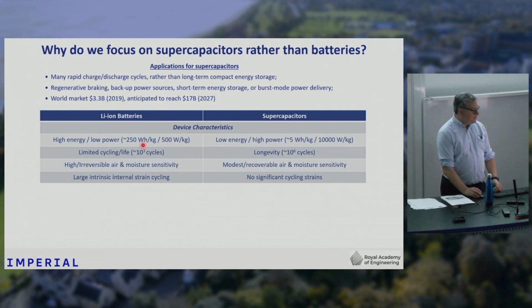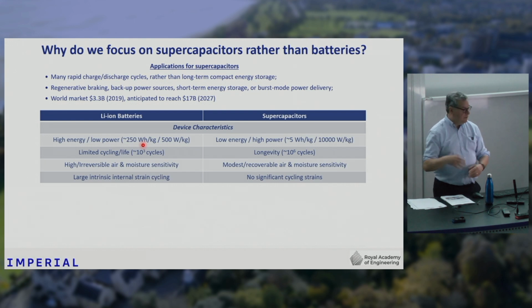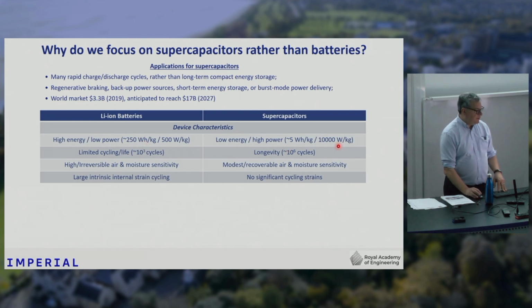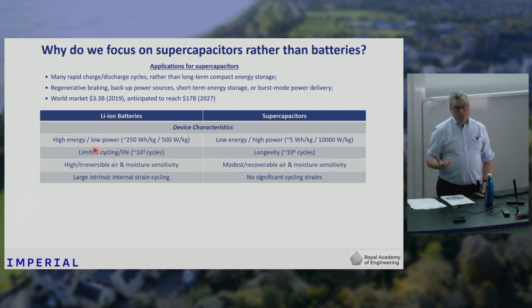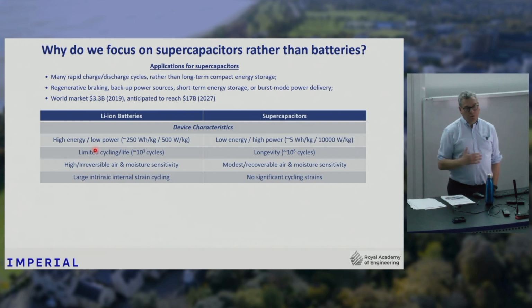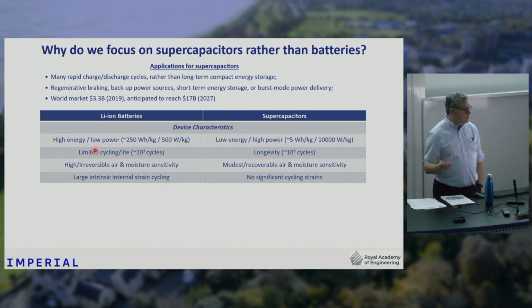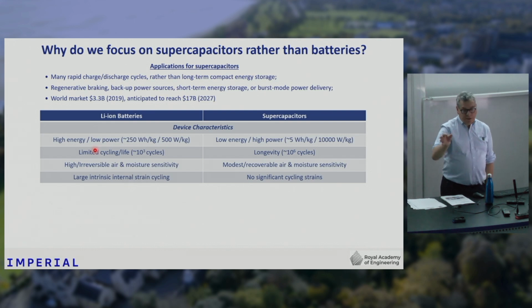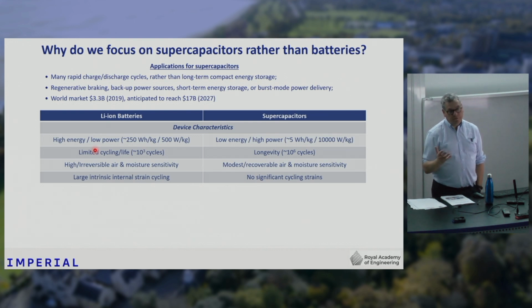Giving you a comparison, lithium-ion batteries give high energy but low power. Supercapacitors are the other way around, low energy, high power. As we're all familiar with, conventional batteries in your phone have a limited cycle life. Your batteries die after a few years' use. A lithium-ion battery is on the order of 1,000 cycles, because you're essentially doing some chemistry. When you charge and discharge, you're actually changing the chemistry of your material. Supercapacitors have a life in excess of 1 million cycles, so they're very attractive from that point of view.